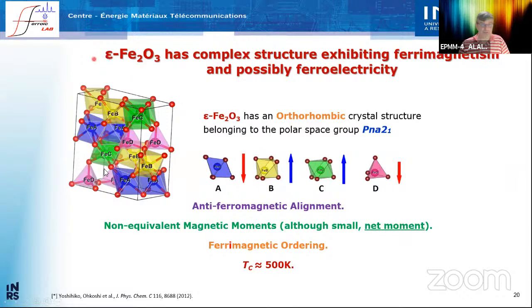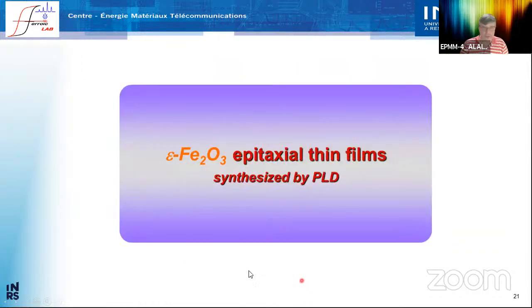Epsilon ferrite has a pretty complex crystal structure. You see, you have the oxygen octahedra, you have an oxygen tetrahedra here, and you have an antiferromagnetic coupling, but because this one is smaller, that's ferrimagnetic, you have a net magnetic moment upwards in this case. Because of the orthorhombic crystal structure, the space group Pna21, this group is a polar group, so this material is at least pyroelectric and potentially ferroelectric as well.